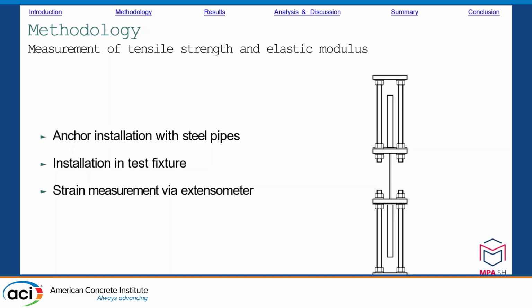Before the tensile test to determine the tensile strength could begin, anchors in the form of steel tubes had to be installed at the ends of the test bars. These were filled with an expansion mortar. After a sufficient curing time, the bars were installed in the test facility and tested. During the tensile test, an extensometer was attached to the center of the bar to measure its elongation. Before the first fiber break occurred, the extensometer was removed. The rebar was loaded in tension until a complete fiber break occurred.